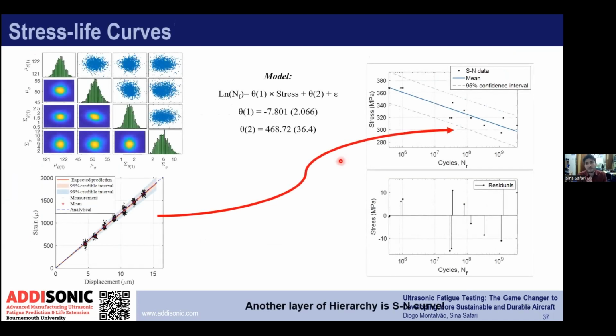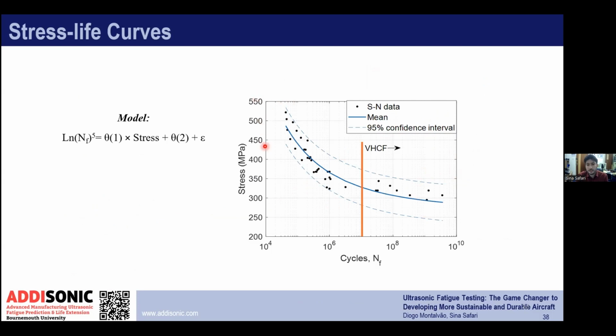So when we built that relationship, now we have the tip displacement and strain. Now we can go and find out the number of cycles for that strain or stress level. Right? So for example, I'm going to excite the machine at a tip displacement of 10 micron. Based on this bottom left graph, that represents, for example, a strain higher than 1,000 microstrain, and then I can build the relationship between the strain and the number of cycles. So these are the data points based on the 12 specimens we just broke for the very high cycle regime, and we had some data for the low cycle regime as well.